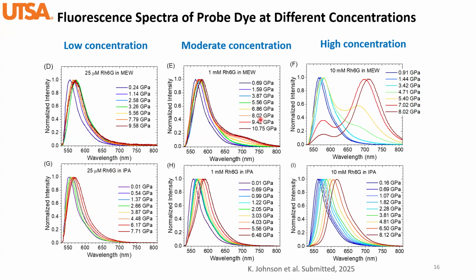And when we consider that you don't have this peak here, it does not mean that IPA does not form aggregates. Actually, rhodamine 6G solubility in IPA is much, much lower as compared to methanol, ethanol, and water.